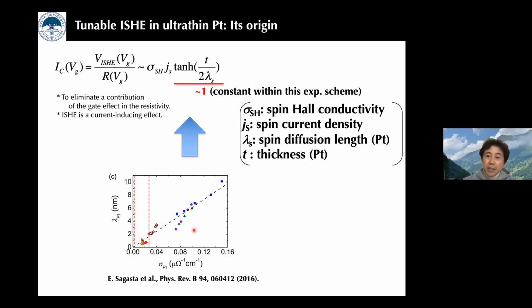To understand the physics behind it, we focus on the gate dependence of the electric current generated by the inverse spin Hall effect. Here I emphasize that the inverse spin Hall effect generates electric current, not voltages, because spin scattering is the origin of the effect. The generated electric current is equal to the inverse spin Hall voltage over the resistance of the film, and the important point is that both are gate dependent. In consequence, the generated electric current is proportional to the product of the spin Hall conductivity, the spin current density, and this tangent hyperbolic term.